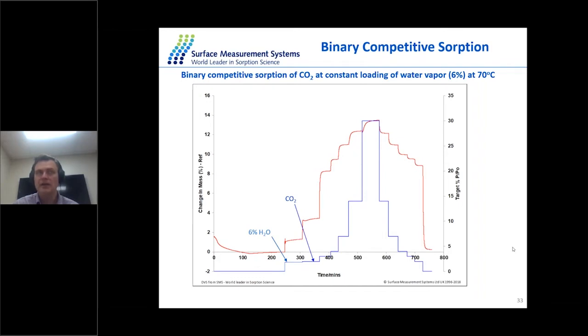And the second benefit of gravimetric over volumetric systems when you do vapor or gas adsorption is kinetics. In a gravimetric system, you always see the kinetics, so you can see whether you reach equilibrium. In many volumetric systems, you hardly get access to the kinetics, so you don't see the equilibrium data. In some cases they might release it, but what you usually see is points on the screen for your isotherms. For many of these experiments, especially with new novel materials, it's quite important to see the kinetics. I measured some CO2 adsorption at the 400 ppm level, and if you don't see the kinetics, it's very hard to understand whether you reach equilibrium or not, because most of these adsorption materials are adsorbing forever. So kinetics is the other important parameter of the gravimetric system versus the ASAP 2020.